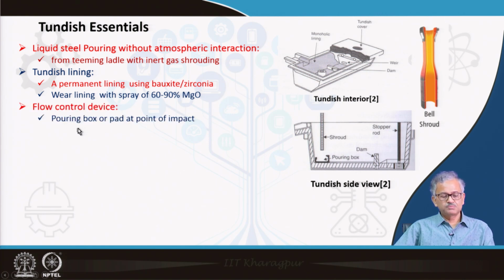Flow control device, pouring box: you can find that here is a pouring box. When you are teeming the liquid steel from the ladle to the tundish, the liquid will fall directly and have a huge impact on the refractory. Not only that, it will create a lot of turbulence in this region. So to dampen that turbulence and to avoid direct contact of the liquid stream with the refractory lining, basically you use a pouring box or pad at the point of contact.